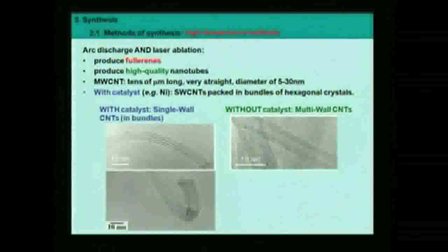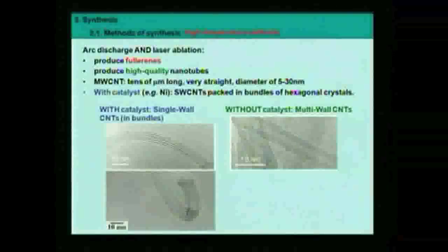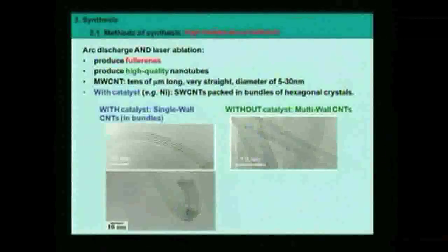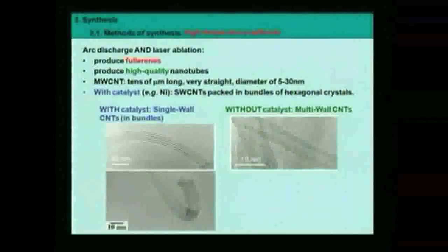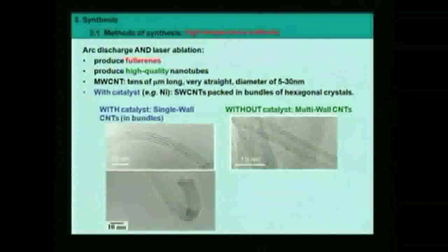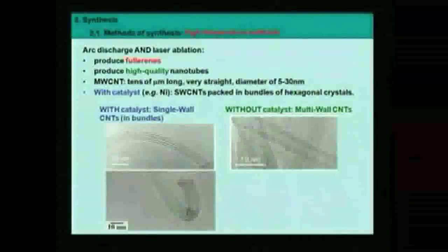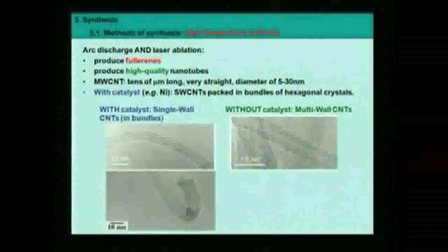And as I said before, if we add some catalyst like nickel or cobalt together with the graphite, then we will observe experimentally that the obtained products are no more multi-wall nanotubes or fullerenes, but single-wall nanotubes as observed on those pictures. Here you see a bundle of several single-wall nanotubes packed together as we already saw yesterday.